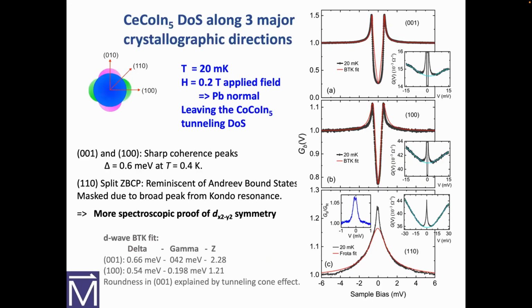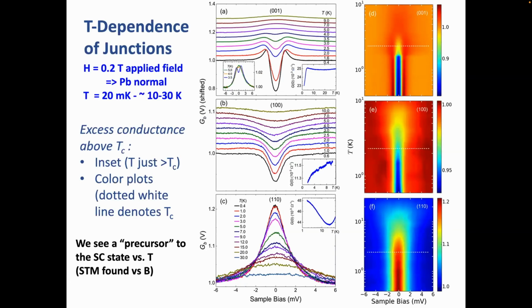So here's some original data. The top plot is the C-axis direction, 001, and the one next down is the A-axis direction, 100. And if we analyze all this, it's very clear. Further support is dx squared minus y squared. Looking in the nodal direction, the 110, there are certain things that are consistent, but I cannot explain why that zero bias conductance peak is so broad. So we kind of left that behind. We do things that convince us that it's the nodal direction and it's dx squared minus y squared, but I can't really fit that entire background. But if we do a BTK fit to this, we get reasonable results of dx squared minus y squared. Now, this is the temperature dependence.